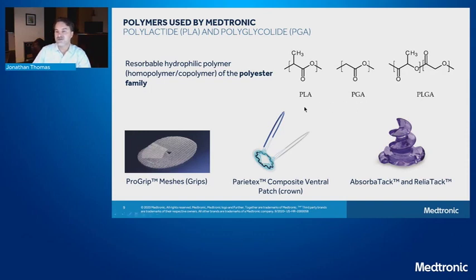What's really interesting is if you can take these different polymers and modify their chemistries in different components, you're able to get completely different properties. The example of that was 82% lactide and 18% glycolide to make a tack with its durability and how long it takes to go away in the body. Likewise, if I take a 90% glycolide and 10% lactide composition, what you're going to be left with is roughly the composition that's used in Polysorb or Vicryl sutures. And it has a much shorter decomposition or absorbable time frame.